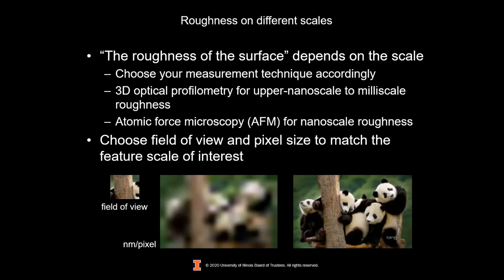Whichever technique you're using, make sure that you choose a field of view that gives you enough information. If I wanted to build up this entire image, and I took a very small field of view, I couldn't just choose one. This is not representative of the entire image. I'd have to do a lot of measurements. Also, think about both the resolution of the technique itself and also the pixel size, to choose an appropriate number of nanometers per pixel or hundreds of nanometers per pixel that matches the feature scale that's relevant to